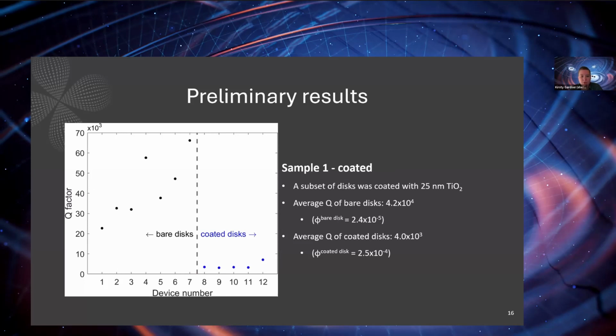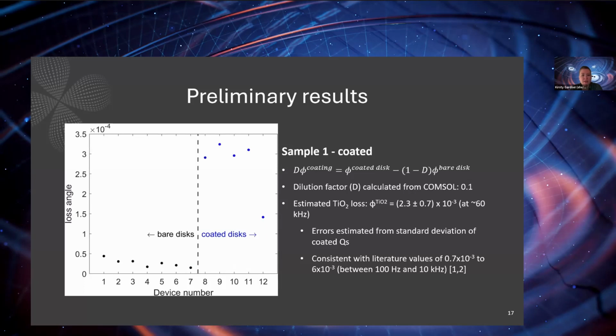Going back to sample 1, before we had figured this out, now I'm showing you, in addition to the quality factors of the bare disks, I've added in blue the quality factors of the disks after we had put coatings on them. The quality factors of the bare disks are of order 10^4, and the quality factors of the coated disks are of order 10^3. We can plot instead the loss, which is just the inverse of the quality factor. That's useful because the formula which relates the loss that you measure of a bare disk and the loss that you measure of a coated disk to the loss that you want to extract of the coating itself uses the losses.